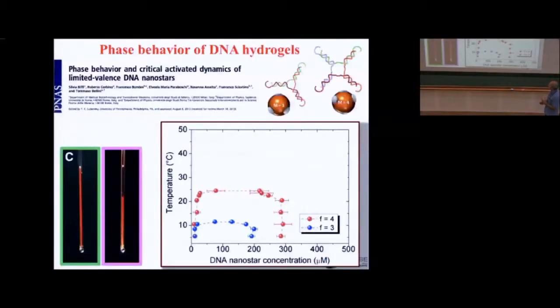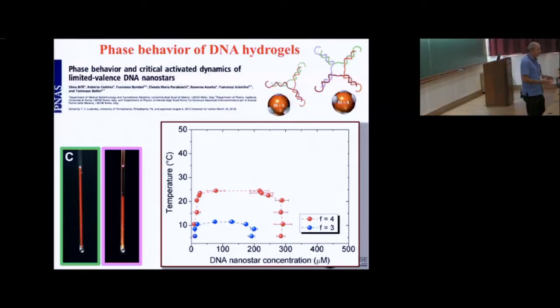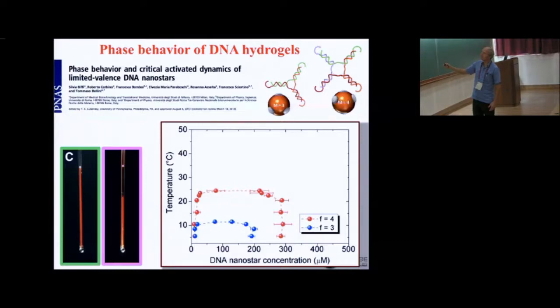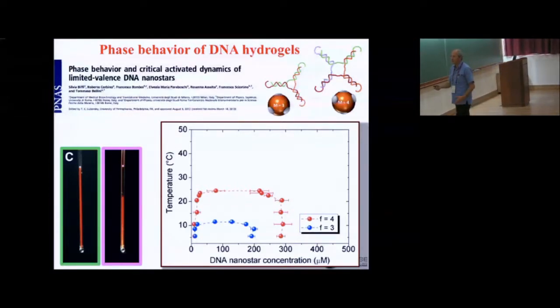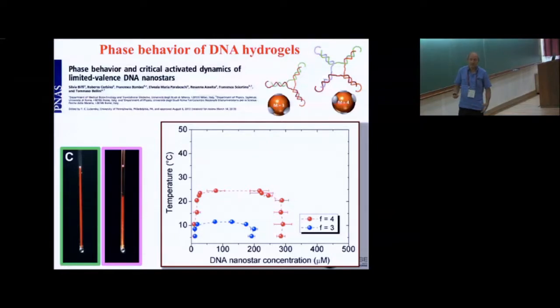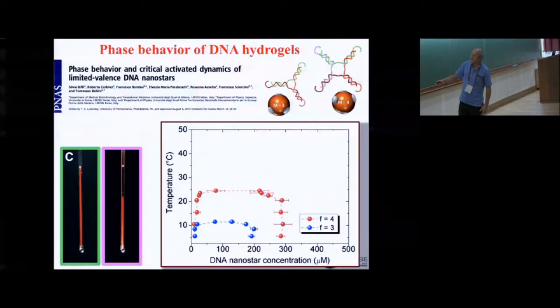Let's see the tests that we can make. First of all, let's test this idea that the phase diagram is controlled by the valence. Now, compared to the previous experiment, we are selecting the number of bonds and the strength of interaction. So we have prepared DNA nanostars with valence 3 and DNA nanostars with valence 4. We have prepared the samples and studied the phase behavior in temperature and concentration. And what you see is that at high temperature, the system is homogeneous. And then if you work at low densities and cool down, you phase separate into a gas phase and a dense phase of DNA.